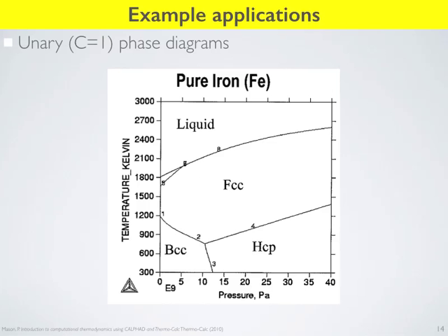One way around this, and we will see this in the walkthrough, is that we can remove particular phases from the calculation. We say, okay, the timescale for iron to turn from FCC to HCP is on the order of years, and so I'm not even going to consider HCP in my calculation. So that's one way of sort of cheating. But just do bear in mind, with equilibrium calculations, you might not see agreement with the experiment for kinetic reasons. Okay, so an important point.